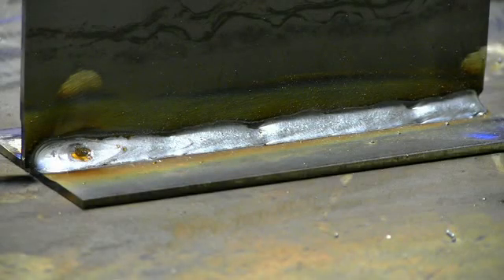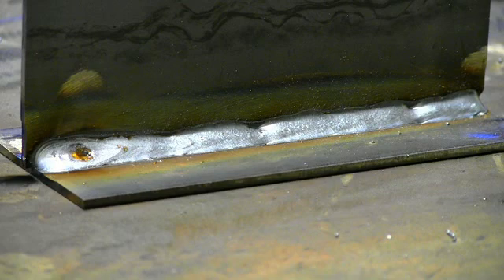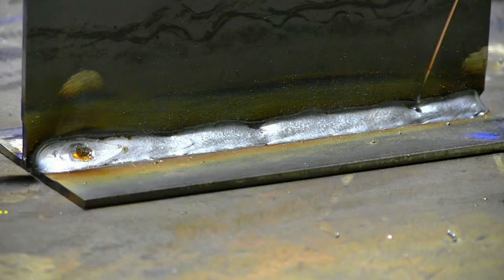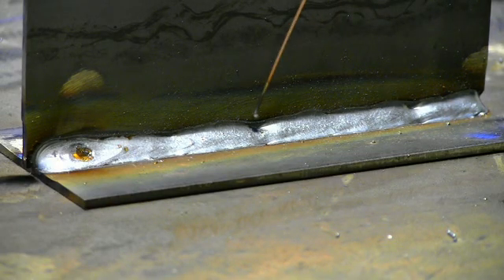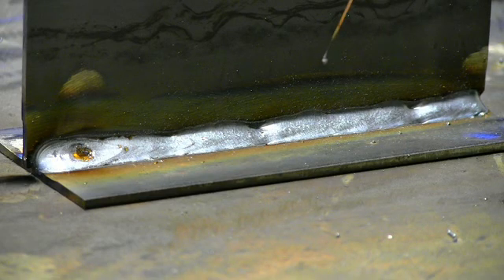So now you can see the finished weld bead with that higher voltage, and the arc was very quiet. There is absolutely no spatter present. However, you can see that the puddle was difficult to control. You can see some voids here and here where it was difficult to control the puddle. And so you've got to be really careful when welding at those higher voltages.